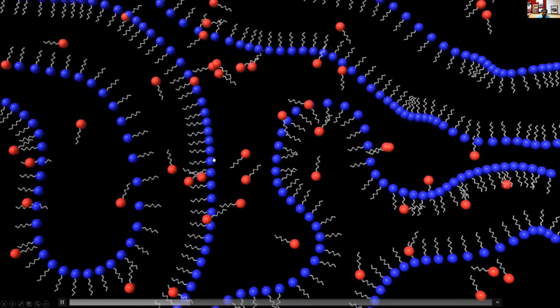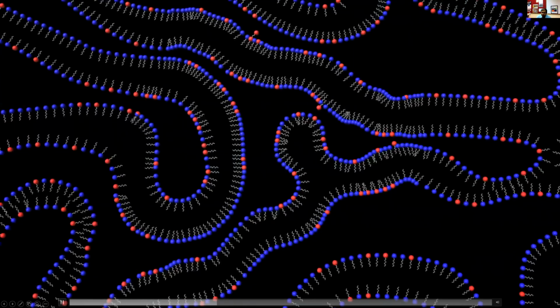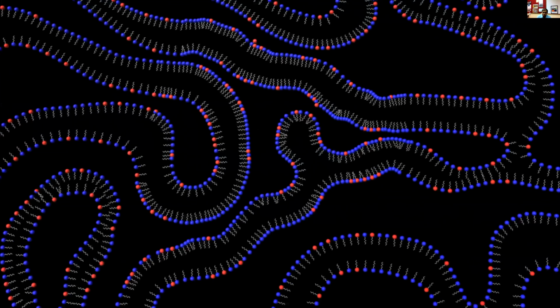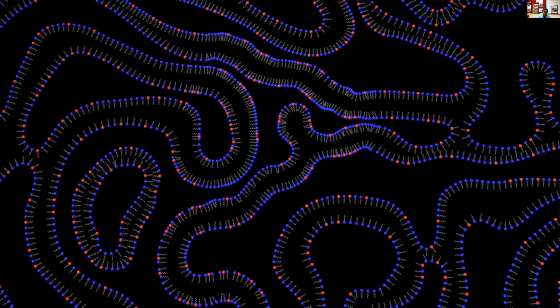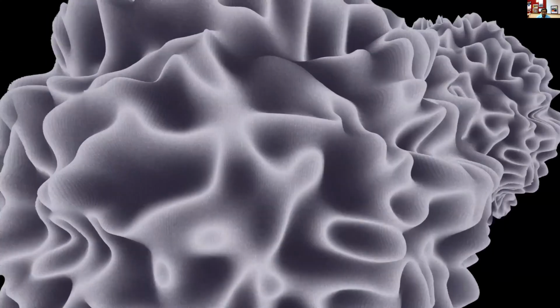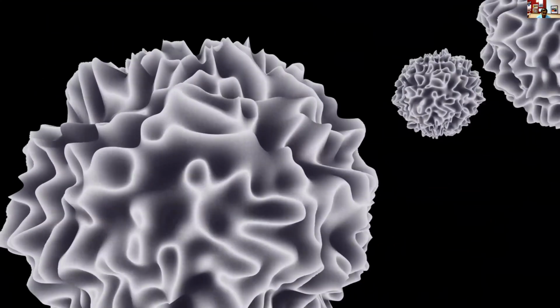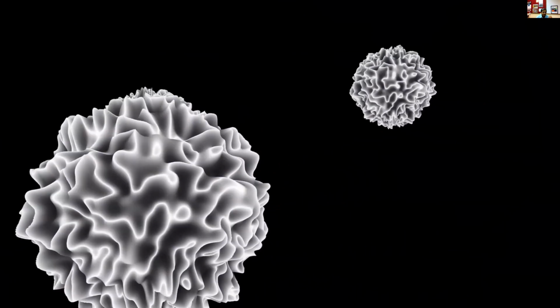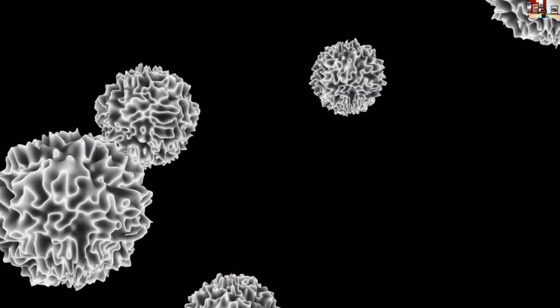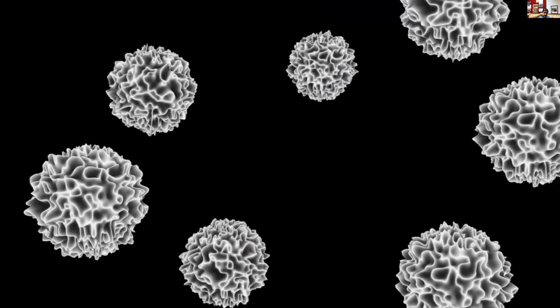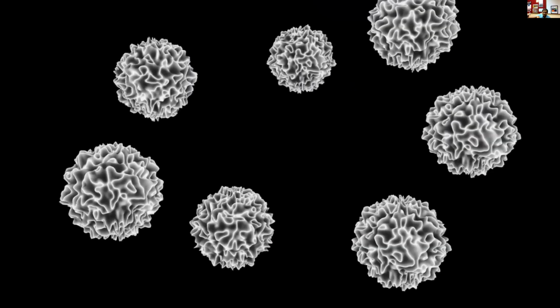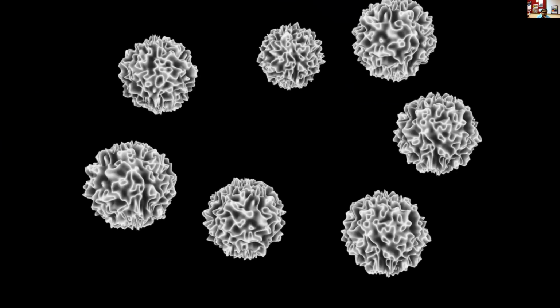And what we observe is that these lamellar phases are not floating flat in the solvent, but are in the form of a microemulsion droplet, a bicontinuous microemulsion droplet, because we have xylene and water trying to continuously mix. And these bicontinuous microemulsion droplets, BMDs, are just made up of water, xylene, and CTAB. So these are the template. These are the nano template. And in the water channels, I have a silica precursor, which will then hydrolyze, condense, and form the silica within the channels.